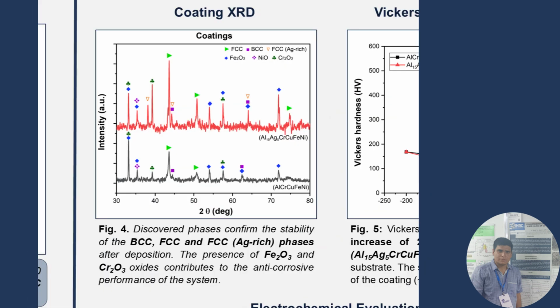The X-ray diffraction patterns of the coatings confirm the structural stability of the main BCC and FCC phases. Crucially, the X-ray diffraction analysis reveals that the thermal energy from the post-deposition sintering process triggers the nucleation of a new, distinct silver-rich FCC phase. This phase separation is a unique feature of the sintered coating and does not occur in the mechanical alloyed high-entropy alloy powder form. Additionally, the formation of minor iron and chromium oxides contributes positively to the system's protective surface behavior.